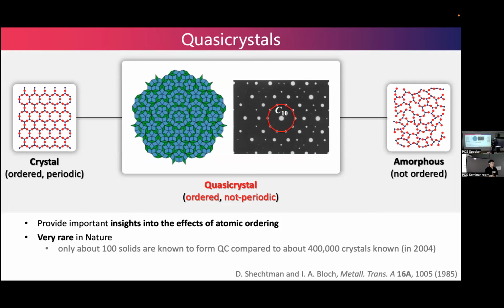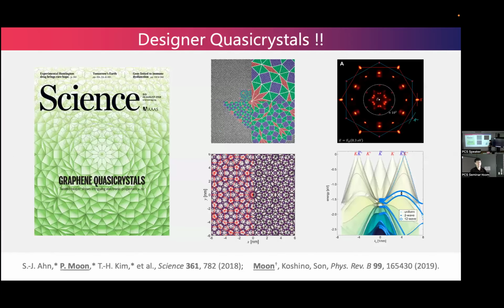What is a quasicrystal? A quasicrystal is a unique system which is ordered but not periodic. So it is expected that it can provide important insight into the effects of atomic ordering between periodic crystals and amorphous solids. But to study such a challenging topic, the number of quasicrystals in nature is very small. Only about 100 solids are known to form quasicrystals. However, we show that by stacking two layers of graphene at 30 degrees, we can design and make the quasicrystal structure. This is a TEM image and ARPES image measured in experiment, and we calculated the electronic structure.